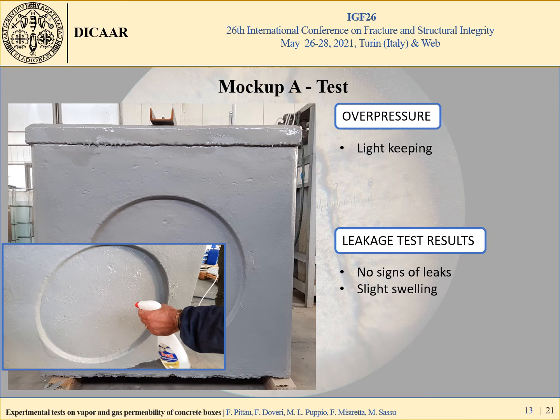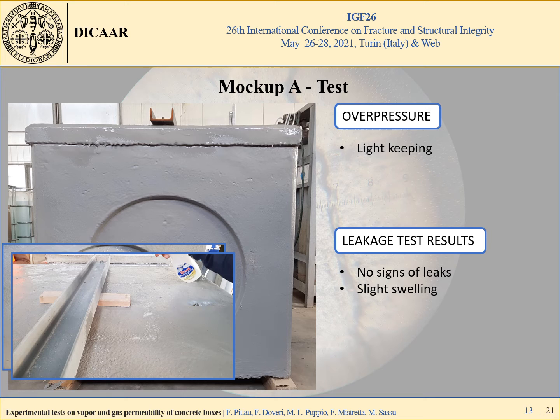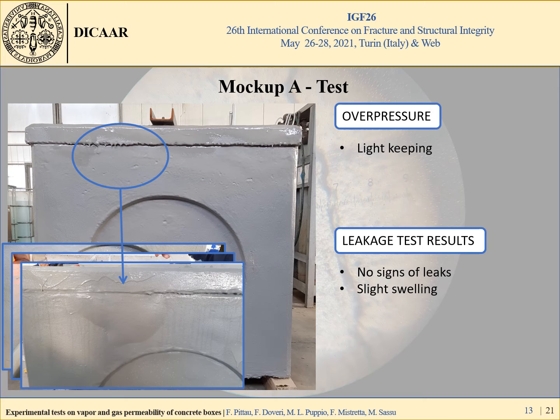Here we can see a picture of the gas leak test. The only problem is a slight swelling near the lid here, but this has been attributed to the imperfection of the surface on which the coating was applied. At the end of the test, when the pressure dropped, the swelling disappeared, a sign that the material remained in the elastic range and was able to absorb the stress.